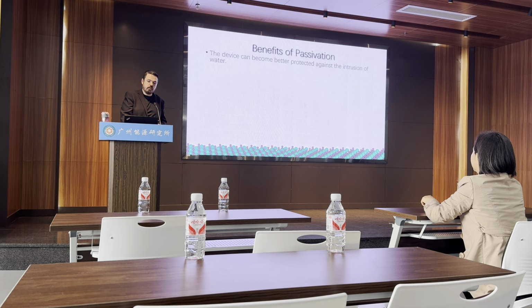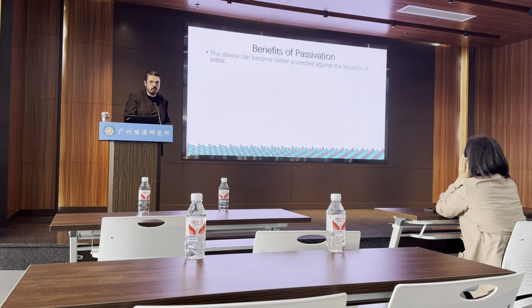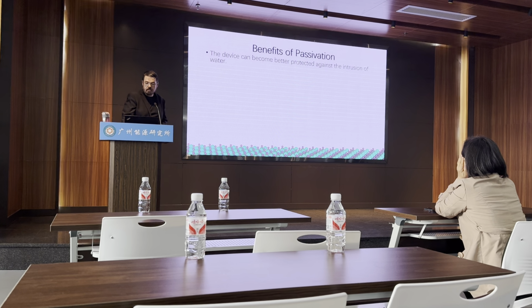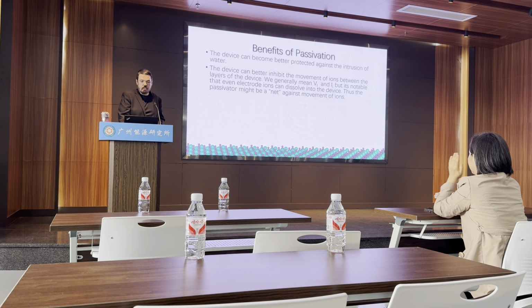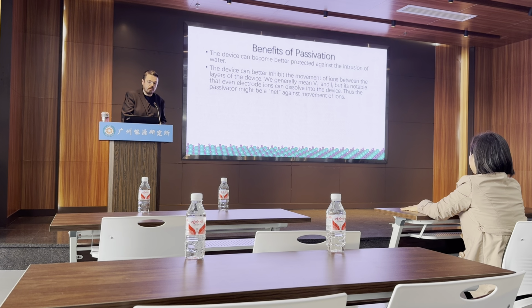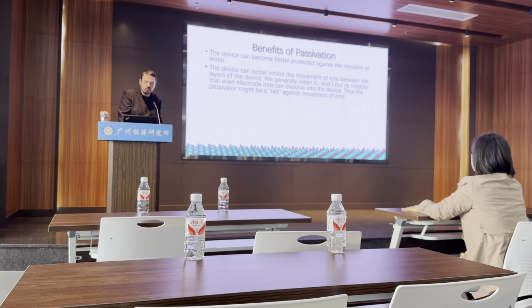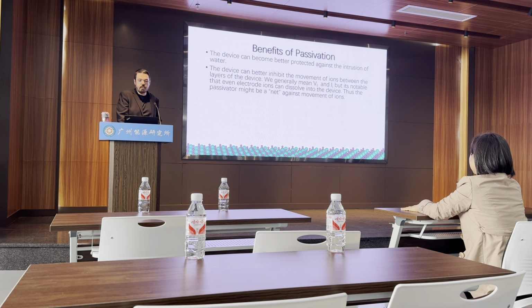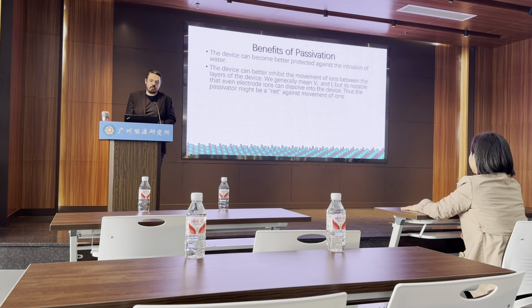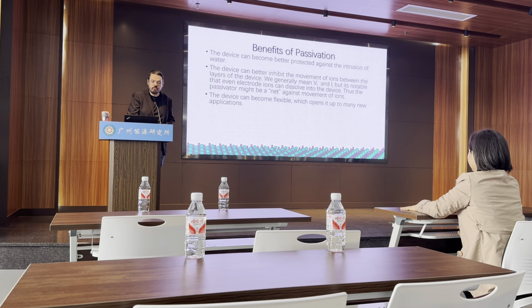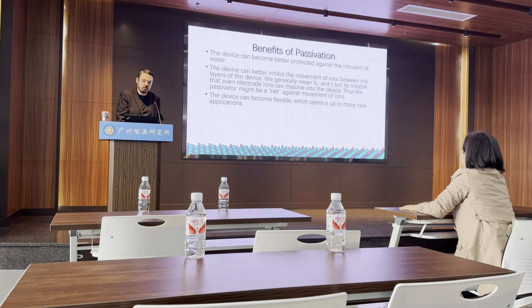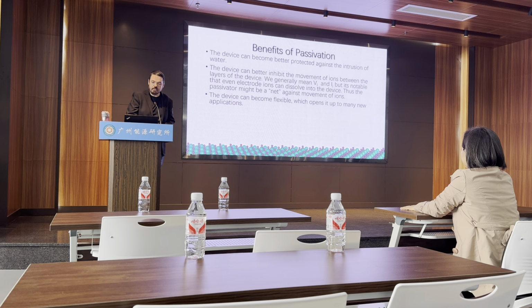Currently one of the big topics is how we protect it from water, because obviously a solar cell has to be outside, so it has to be protected from humidity and water. The device can better inhibit the movement of ions, because it's generally believed that this movement is actually deleterious. So in general, we really mean the iodine vacancies or the interstitial iodines. And it's notable that there's experimental evidence that these can get all the way to the electrode. So the perovskite is actually very corrosive. It's actually a very challenging topic, which is why so many people are at work, obviously.